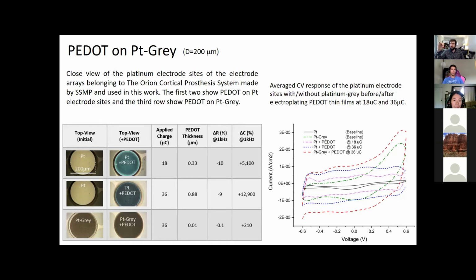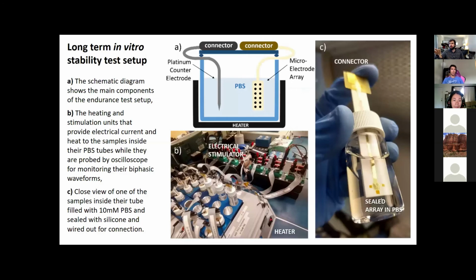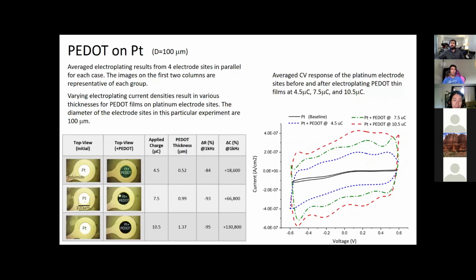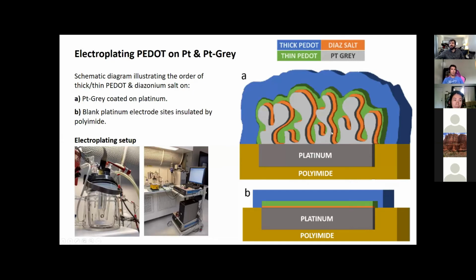So I did the chemical adhesion promotion and electroplated PEDOT on platinum gray, which creates a hybrid scenario. If you look at this, you're creating a chemomechanical situation. This orange one is already creating a covalent bond between this PEDOT molecule and the platinum gray. That's already improving adhesion. And overall, this maze of 3D geometry is working great at encapsulating and entrapping these PEDOT molecules, so you're also mechanically improving the adhesion promotion here.